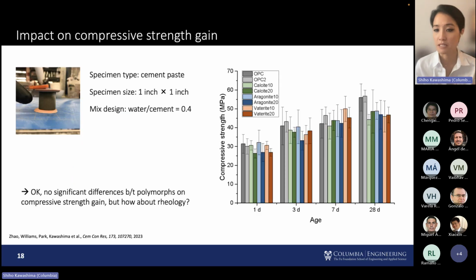And we see similar trends in compressive strength gain. So these are the compressive strengths of pretty much the same material systems that I've shown thus far. So OPC compared to calcite, aragonite, and vaterite at 10 and 20%. And basically what we see is that OPC is the highest by 28 days, and the others are comparable.